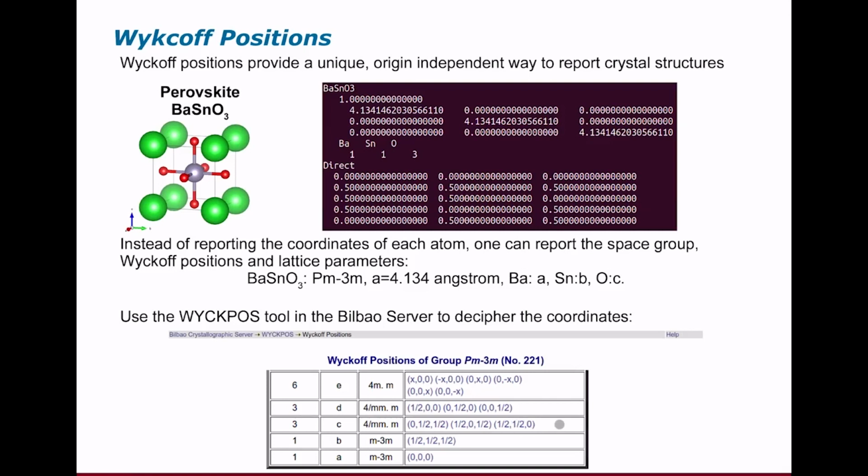There are larger unit cells. Sometimes, for example, you might have a unit cell with like 20 atoms, 50 atoms in it, where you might have, for example, 10 oxygens, but not all oxygens share the same Wyckoff letter. In that case, these oxygens have different densities of states. They would be chemically distinct. And this turns out to be important, especially when you talk about things like charge disproportionation or mixed valence compounds and so on. You necessarily need this sort of separation in the Wyckoff letters.